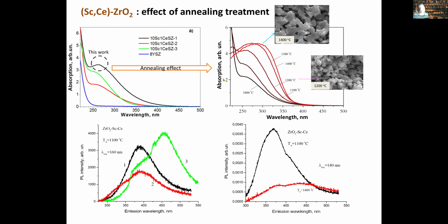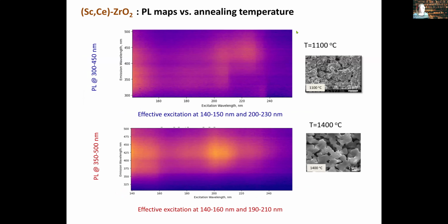Indeed, as we know from application in solid oxide fuel cells, we measured conductivity of these materials. For samples annealed at 1,400 degrees Celsius, the conductivity is the highest. And if we check the structure of these materials, we can see that annealing at 1,400 degrees Celsius results in the formation of huge, large grains.